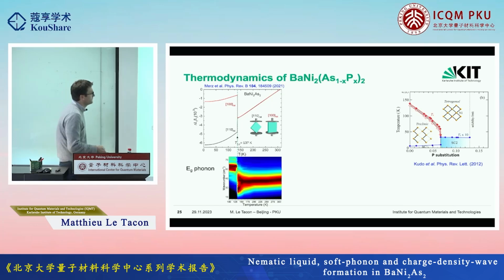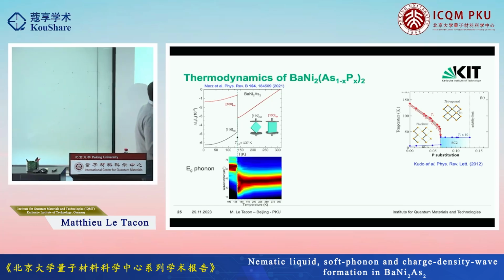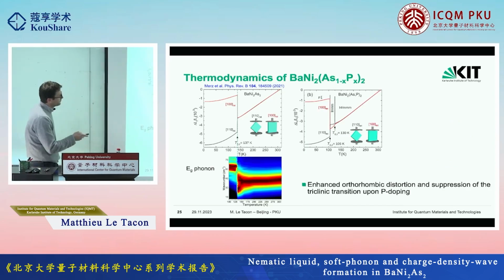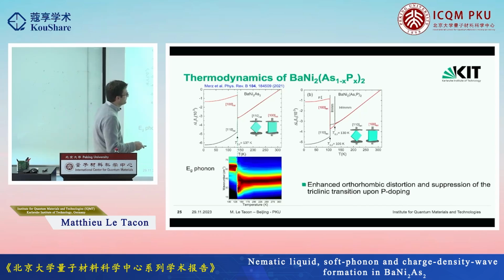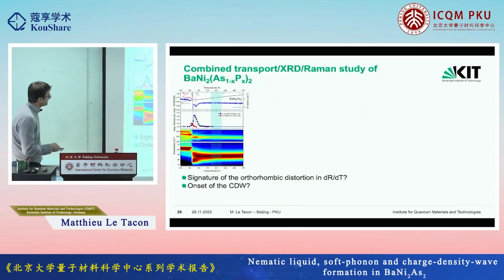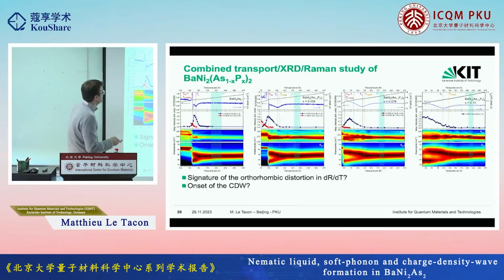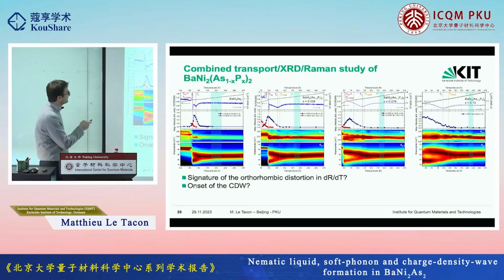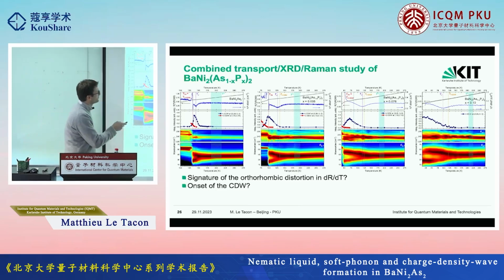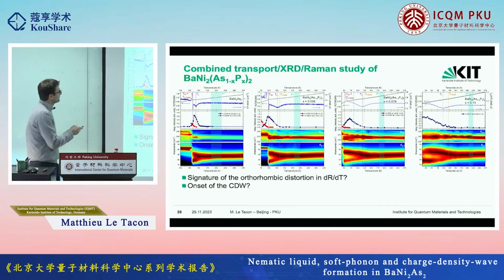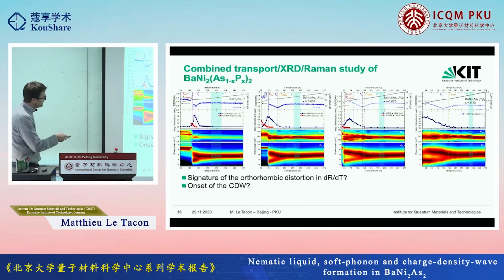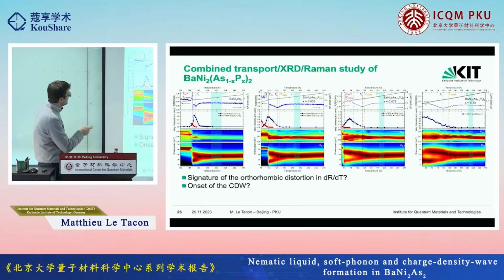We looked at it a bit more carefully as well. Now that's why we went so particularly with the phosphorus doping. So in the phosphorus doping, where the orthorhombic distortion increases when you map it out and try to follow it. Okay, that's what happened as function of doping essentially. So we looked at it with resistivity, and as I said, in resistivity this is a very subtle effect, and actually we saw first something in the derivative of the resistivity, but we're not so sure that this actually corresponds to this. Now we also look at the incommensurate and the commensurate charge density wave peaks, and same thing, the onset basically is always occurring above the temperature at which we can see with our lab diffractometer the formation of the charge density wave, and this is true for all the doping.